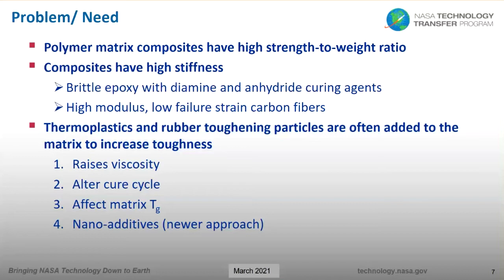Another thing is that some toughening additives may even affect the cure cycle or the glass transition temperature of the matrix, sometimes either delaying the cure or reducing the glass transition temperature. Nanoparticles such as silica and other particles have also been considered as a way to increase toughness of the resin, and this is actually a more recent approach to introducing toughness. But all of those methods that I just described involve adding something to the matrix in order to enhance toughness.